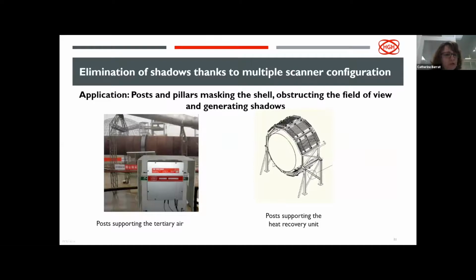As regards the case of posts and pillars, they usually mask the kiln shell and they obstruct the field of view from the scanner, and they generate shadows. So we have to eliminate these shadows in order to see and to measure correctly the temperature of the kiln shell located behind. So you have such examples of frequent application shown here. Here we have posts supporting the tertiary air pipe, and of course behind the post we are not able to measure the temperature. Similarly, the post supporting the heat recovery unit may mask the kiln shell from the scanner.